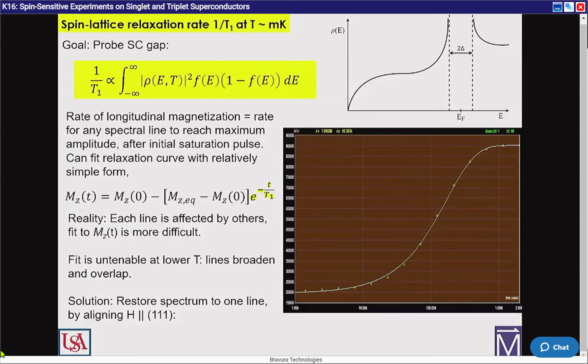And in fact, when you go down to lower temperatures, which was our goal, the lines get broader and they overlap, and it's just a mess. So we hit on the solution of, we have a single crystal. We just align the crystal, so as previously mentioned, so that the field is along 111.